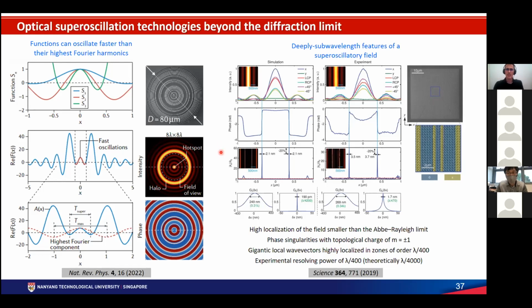But one thing that wasn't realized until recently is that besides the center hotspot, this field carries gigantic wave vectors that are highly localized in zones that go experimentally to lambda over 400. And they've been used even more recently to show experimental resolving power, in this case in metrology, of lambda over 400, which can theoretically reach lambda over 4,000.